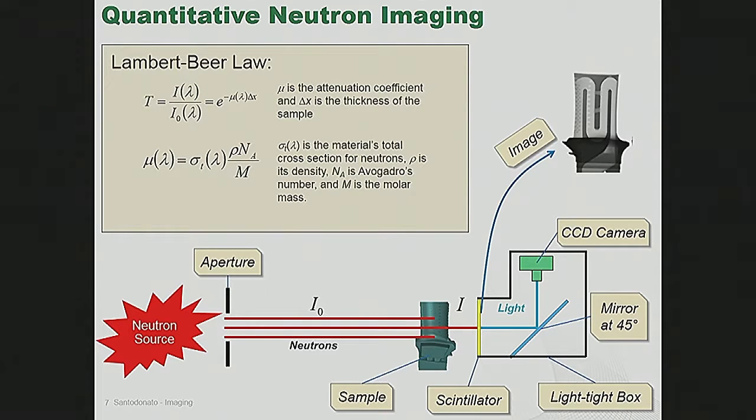The other part that's relevant to the sample is the density of the nuclei. You've all heard already, I'm sure, that neutrons are interacting with the nuclei in the sample. So part of the challenge is that your attenuation is wrapped up in both the cross sections of the atoms in your sample and the density of those atoms. Sometimes that's a challenge to unravel those two effects.